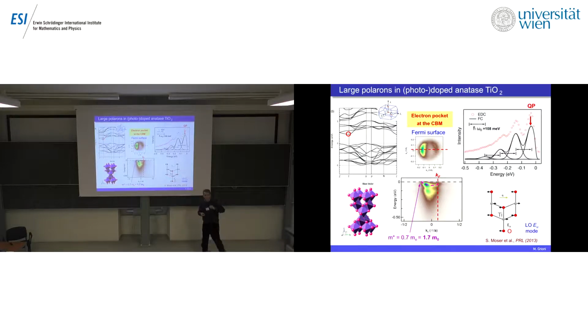We'll hear more from the next speaker, actually, about this system. Titanium oxide, of course, is a wide gap insulator, but in fact, you can dope it. You can introduce oxygen vacancies, and these oxygen vacancies put electrons at the bottom of the conduction band. And there are ways to do it continuously. In fact, you can use light itself to create the vacancies and change, therefore, the number of free carriers.